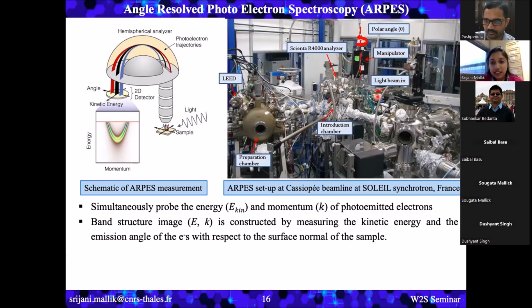This is the ARPES setup in the Cassiopeia beamline, where this is the ARPES chamber, here we have the hemispherical analyzer, and the light beam comes from here. In this setup, we have one advantage: it is connected in situ with an MBE chamber. As I said, this is a surface sensitive technique, so we cannot grow a thick sample and bring it there, as then we will not see any signal. So it's really good if we can prepare our sample here and immediately transfer it in situ to the ARPES chamber and study the band structure. This is what we did.